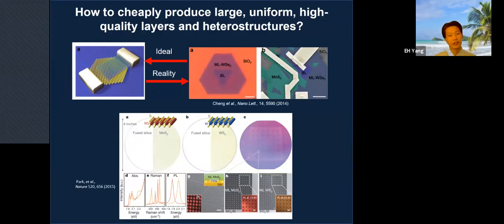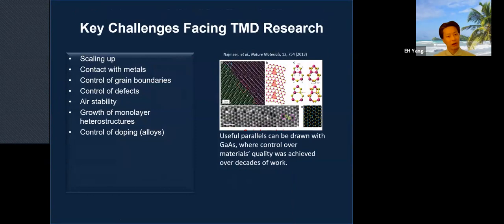So I would say it is still difficult to clearly answer the question of how to cheaply produce large, uniform, high quality layers in heterostructures, right? So you can say yes, but you can say no. It depends on which angle you come from to see this. So scaling up is still an issue, but in addition to this scaling up issue, there are other key challenges facing this TMD research, including contact with metals, control of grain boundaries, and control of defects. Speaking of the control of defects, useful parallels can be drawn with gallium arsenide, where control over materials quality was achieved over decades of work, which means that for TMDs, which are about 10 years old in this area, you probably need another decade or two to achieve the control of defects.